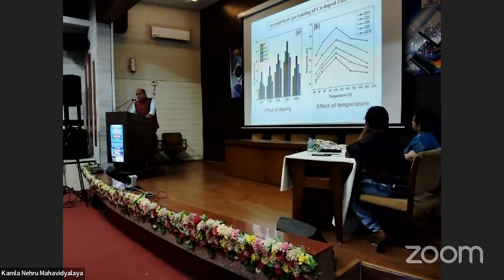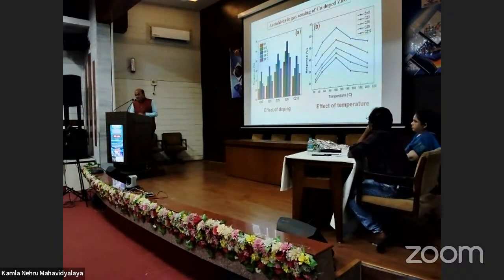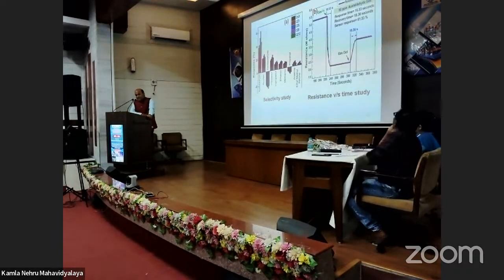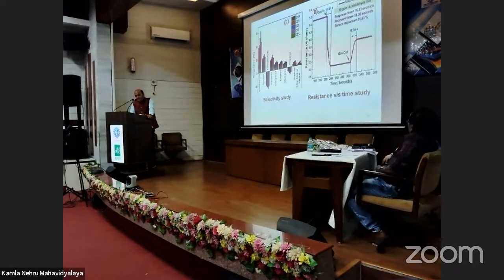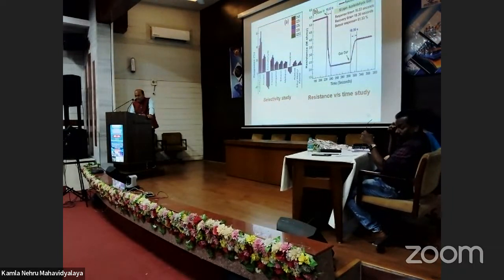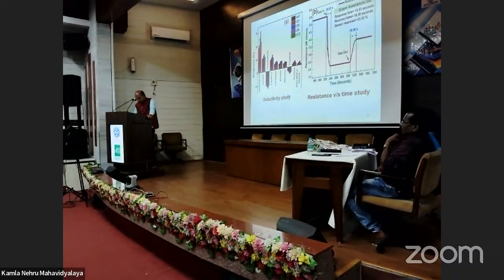We have tested this gas sensor for acetaldehyde. We have taken zinc oxide as well as the copper doping. In this, 9% copper doped zinc oxide shows the best sensing response at 100 degrees centigrade. We have gone up to 200 degrees. Then, in the selectivity study, we observed that acetaldehyde response is best at 9% copper doped zinc oxide as compared to other gases like acrolein, formaldehyde, n-propanol, methanol, then acetone and methyl ketone too. This means the sensor is selective towards acetaldehyde for 9% doping, and the sensor response is up to 60%.